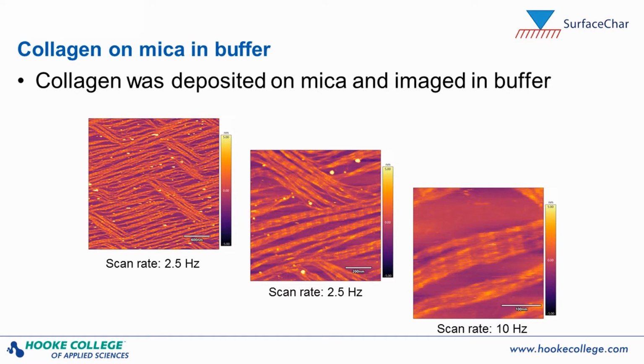Here is an example of taking advantage of the ability to image in fluid with this photothermal actuation and combine it with high speeds, which you typically don't see on these large sample instruments. So this was collagen, which was deposited on mica and imaged in a buffer solution. You can see these collagen fibers very clearly. And this is actually a high resolution image of only about 300 nanometers on a side, where you can really see the fibrils in the collagen fiber here.